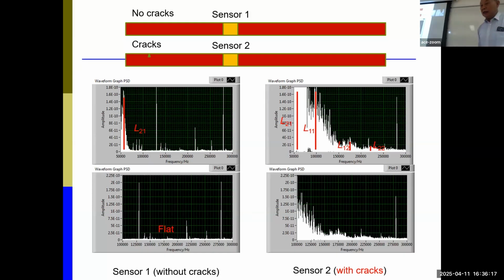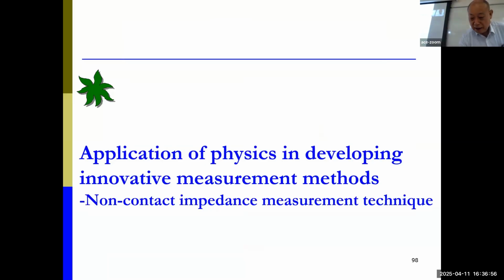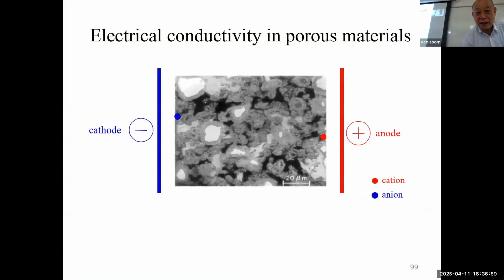You see these two spectra. One is without crack, another with crack. You can see they are quite different. And then we utilize this indicator to show there's a crack. So finally, they passed the examination from the railway department, the Ministry of Railways at that time, before it became a company, and now it produces products for application in the whole of China.